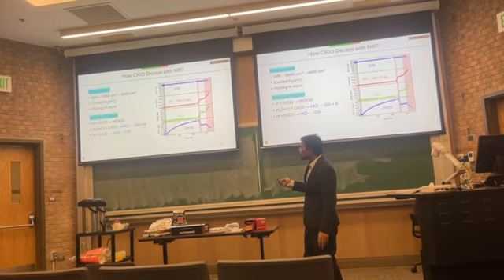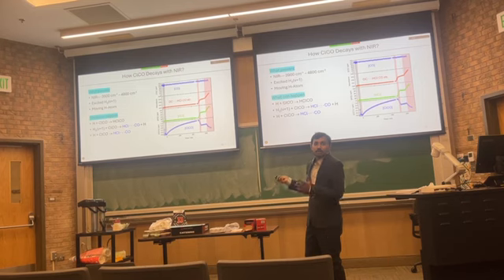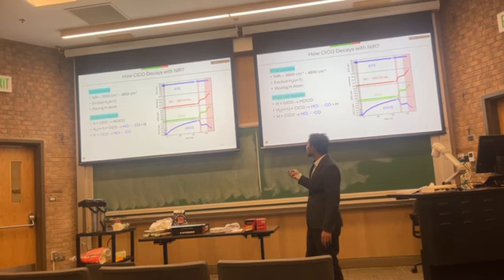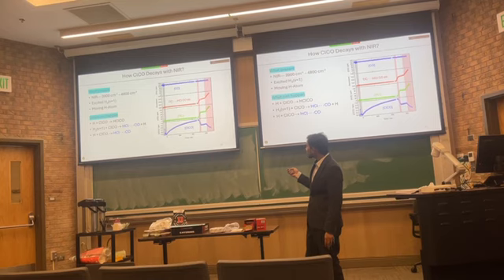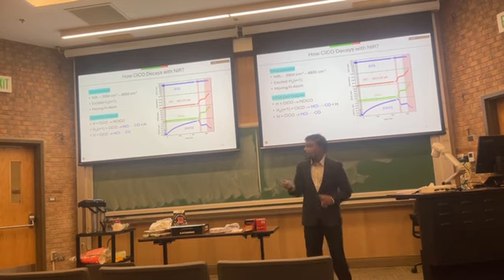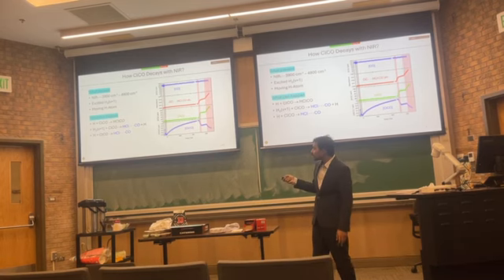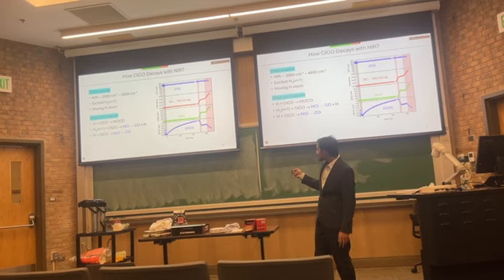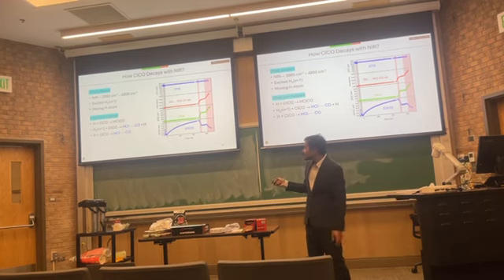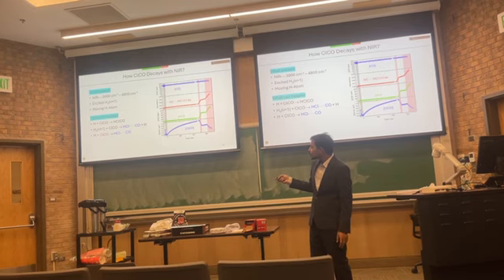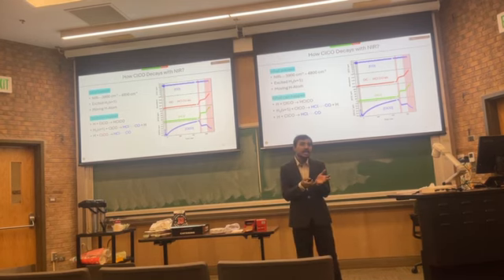That means one of these two can happen. Then we stop our near infrared after 30 minutes. What we see is our HClCO is still growing. At this point, we don't have any excited hydrogen molecule. We only have hydrogen atoms. That means this white part can only happen if a hydrogen atom reacts with ClCO. So that means our third reaction is definitely happening.